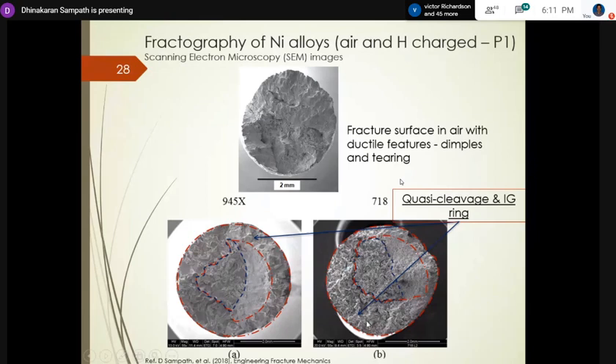And in 718, as I told, the outer region alone has got a lot of hydrogen, and also during the in situ test some more hydrogen is pumped in, so we get this kind of a ring. In 945X, we don't have that kind of ring. It's just skewed, but it showed a mix of cleavage, that means transgranular and intergranular cracking. Trans in the sense it will just cut through the grain, and intergranular, it's cracking through the grain boundary.